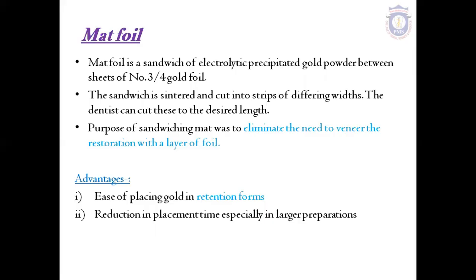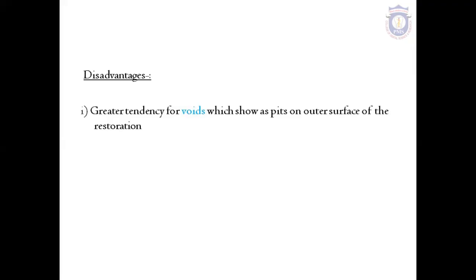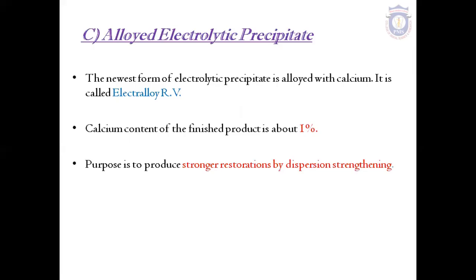The sandwich is then sintered and cut into strips of differing widths. That is, the matte gold strip is sandwiched in between the foil. So the purpose of sandwiching was to eliminate the need to veneer the restoration with a layer of foil. So what are the advantages of this matte foil? Ease of placing gold in retention forms, and the reduction in placement time in larger preparations. And the disadvantages: there's a greater tendency for voids, which are pits on the outer surface.